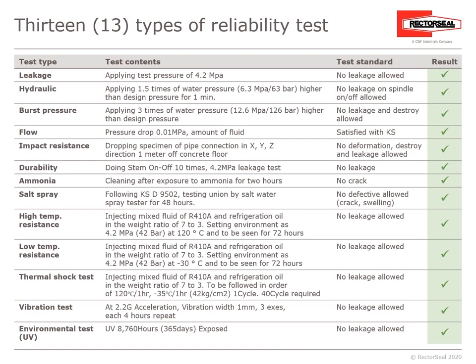And then there's also the flow pressure drop, impact resistance, durability, ammonia, salt spray, high temp and low temp resistance testing, the thermal shock test, vibration test, and an environmental test that is exposed for 365 days. And again, the result was no leakage.